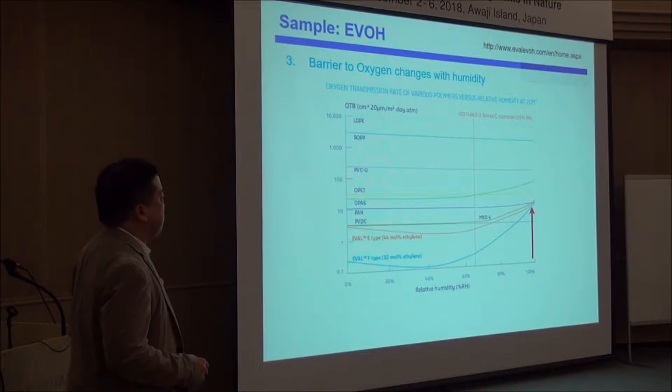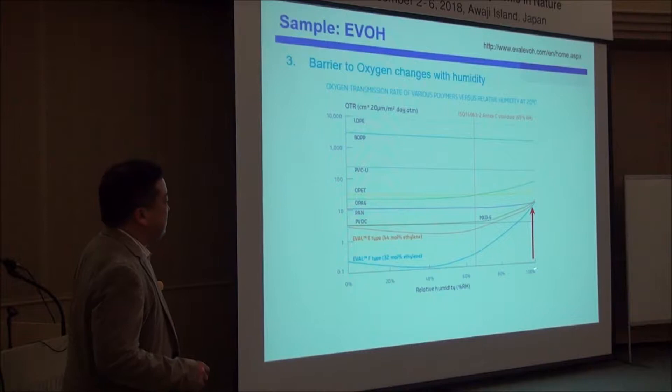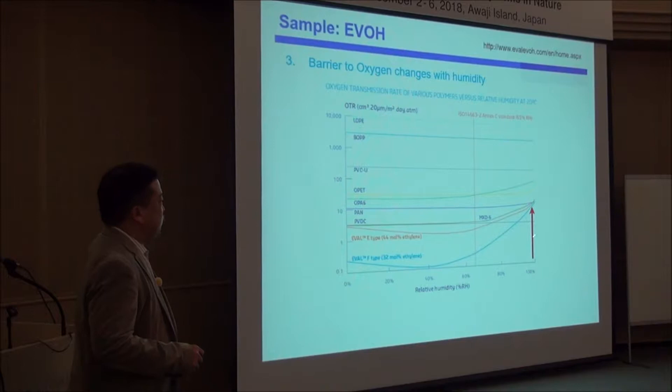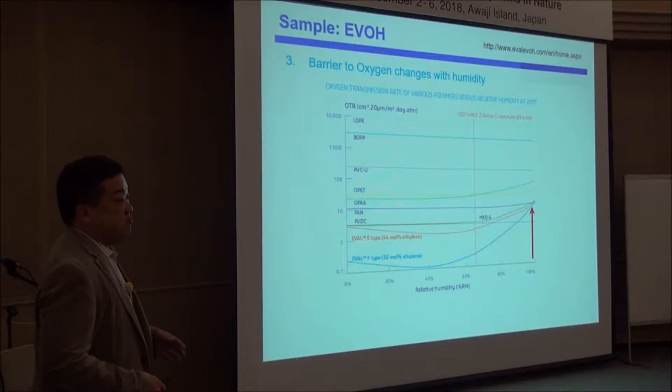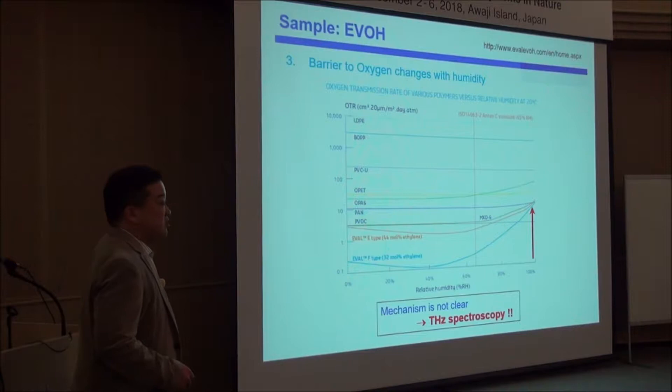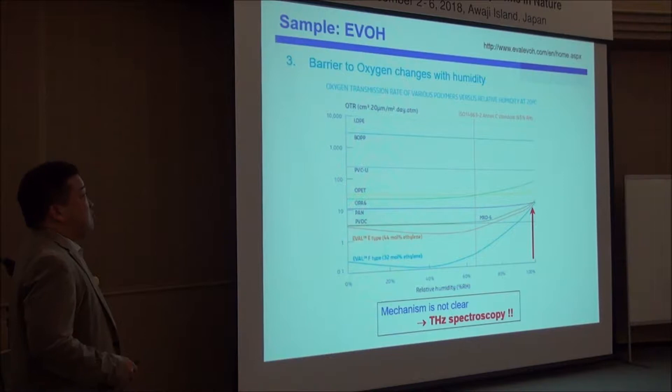There is one problem with using this polymer: it changes its properties with humidity. This is a plot of oxygen transmission rate against humidity, and at higher humidity it becomes the worst barrier. They wanted to know why it changes with hydration. I proposed that we could use terahertz to see the dynamics of water, so we started a collaborative research with Kuraray.